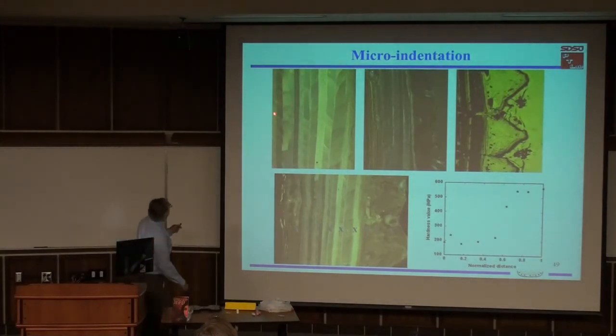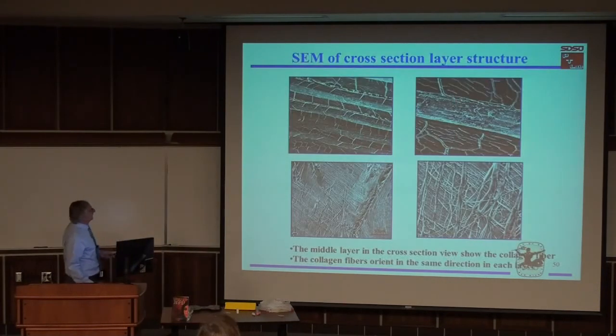And these are the layers here. There are lots of cracks, and these cracks are produced when the scales dry, by shrinkage. And these layers are not at 90 degrees, it's like 75 or 70 degrees from each other. The outside has this serrated, corrugated structure that is highly mineralized. The hardness is like 200 megapascals inside, and it increases to 500, 600 on the outside. And you see all these cracks. I was able to guess an angle just from the pattern of cracks. Every third layer is parallel to this.